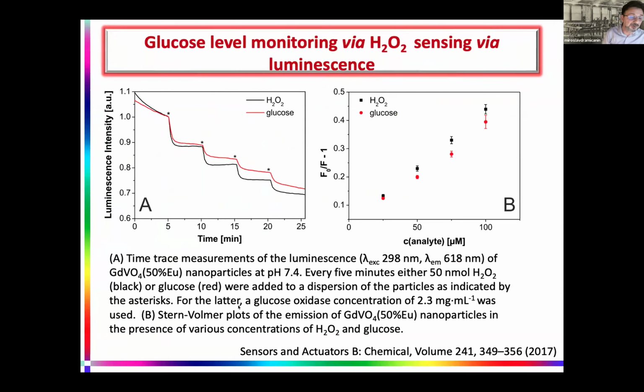It's important because our nanoparticles were not cross-sensitive to anything else except to hydrogen peroxide. And hydrogen peroxide is actually a product of enzymatic reaction of enzymes from the class of oxidases. And there are so many of these enzymes. So let me explain in short. For example, if we want to detect glucose, then we add glucose oxidase, its counterpart enzyme, and as a product, we will get hydrogen peroxide, and it will quench emission. And via quenching by hydrogen peroxide, we can determine the concentration of glucose, for example, in blood.